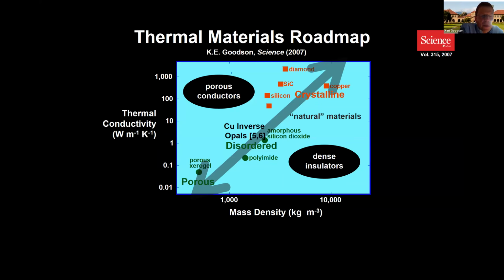Back in 2006, some colleagues had written a great paper, and I was invited to write a perspective in Science. And I spent a lot of time thinking about thermal materials. If you track the density and the thermal conductivity of most materials, they follow a simple proportionality, where as things get denser, they conduct heat better. So diamond up here and copper, 1,000 watts per meter Kelvin ballpark, and then the aerogels, things that were used back in the day to protect the shuttle during re-entry because of very low thermal conductivity, are highly porous. And so things are essentially along this line.